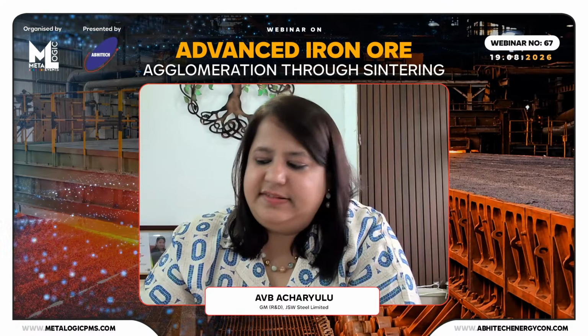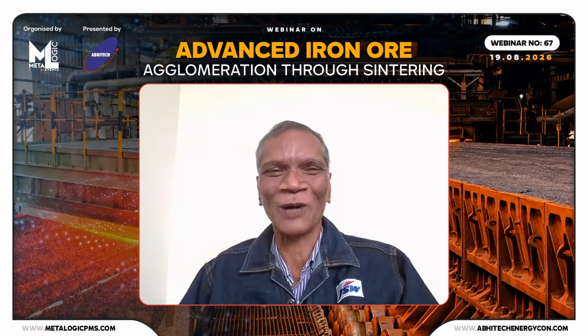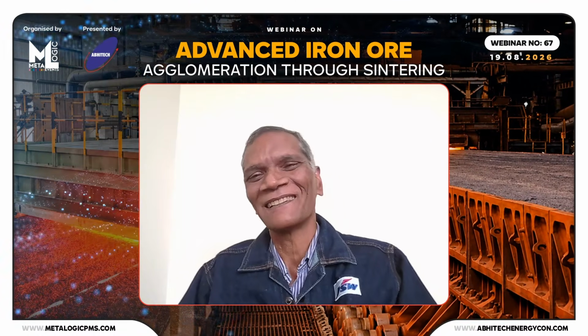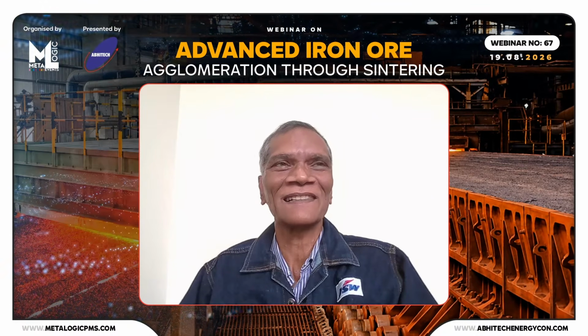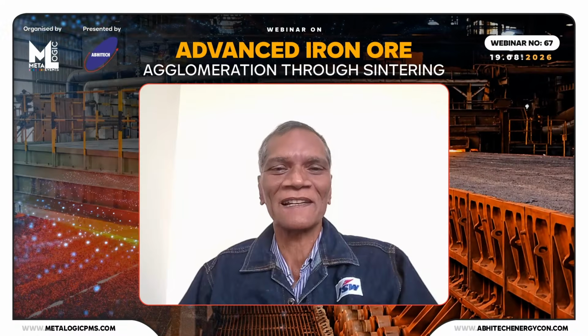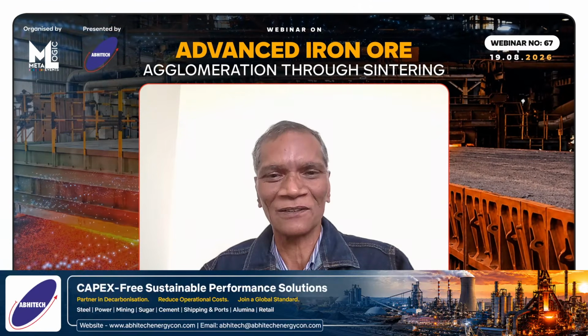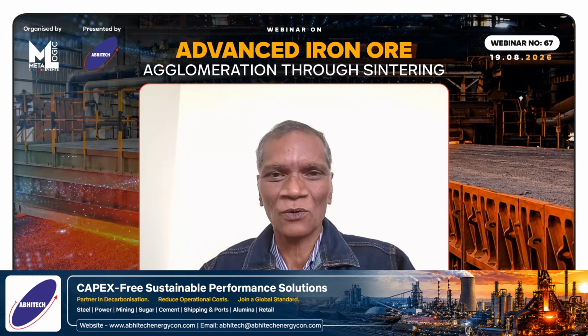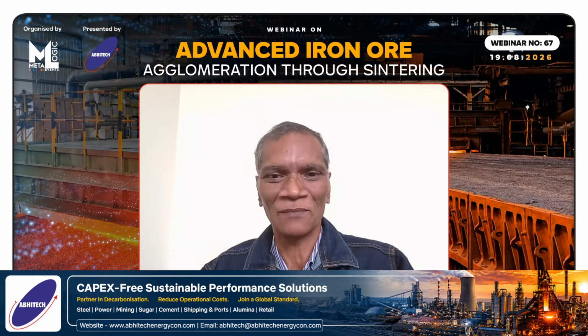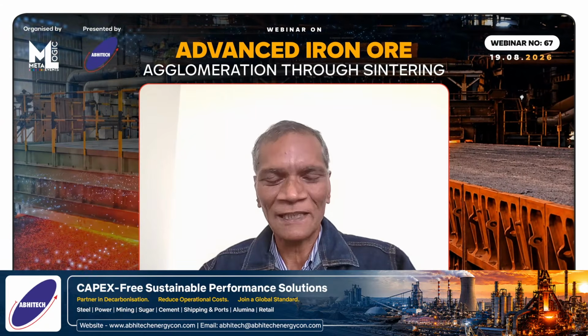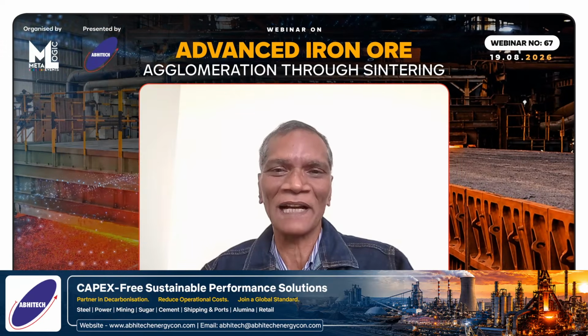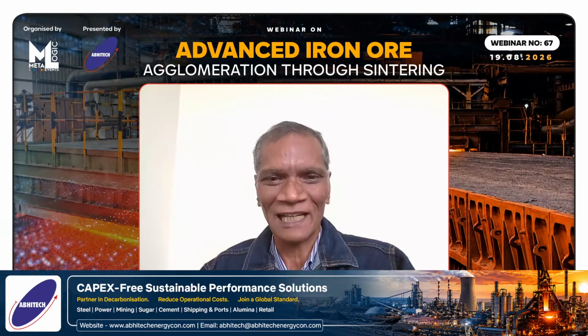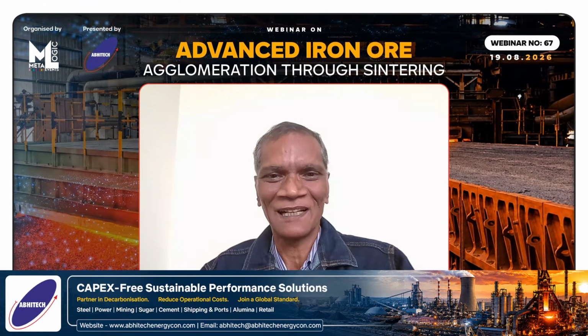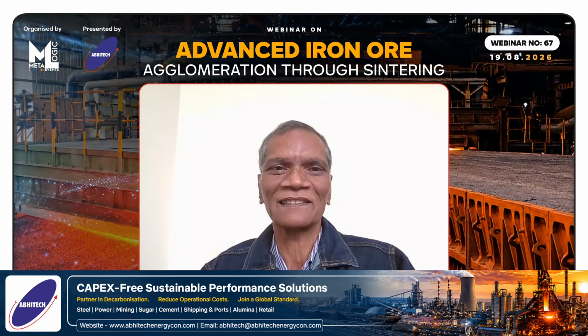Yeah. So if you could tell us which have been the successful ones and which were not successful. No, it's proprietary, so I would not put my comments. But there have been some issues with these alternative binders in the sense that these binders work very well in pellet making because the particle size is small in pellet making. The overall surface area is more. If you look at the input raw materials of the sinter mix, the particle size is large. So to have a coating of this binder, you will require a huge amount of material. In the first place, the binder itself is very costly, and to afford such a large quantity of binder in the sinter making process looks to be economically not viable. Therefore, the attempts are getting limited. But yes, theoretically speaking, they improve the granulation index a lot.